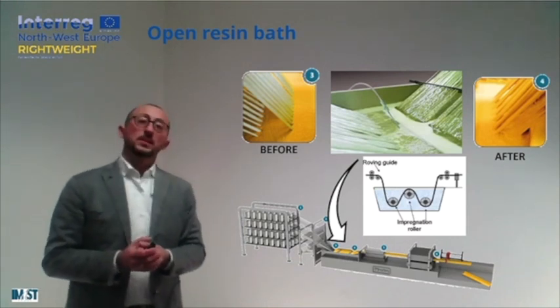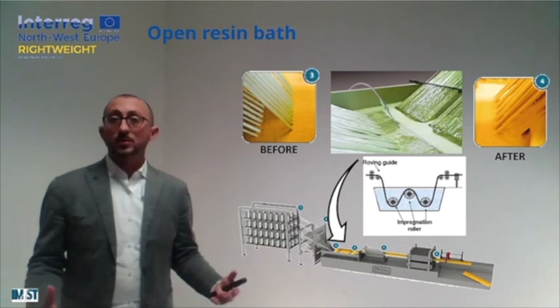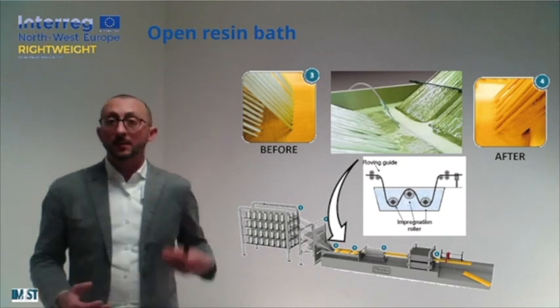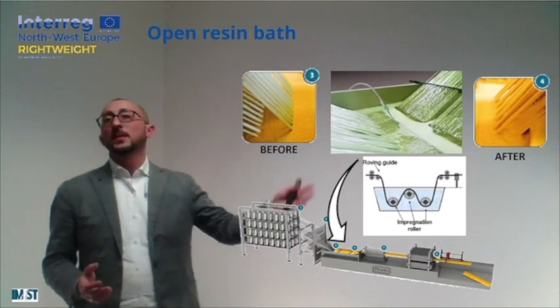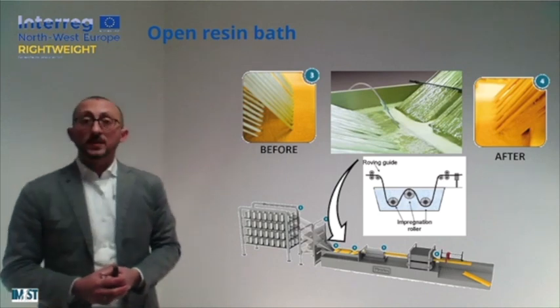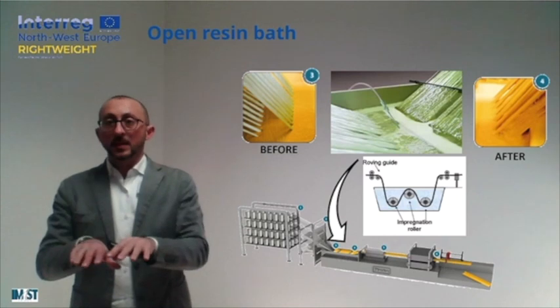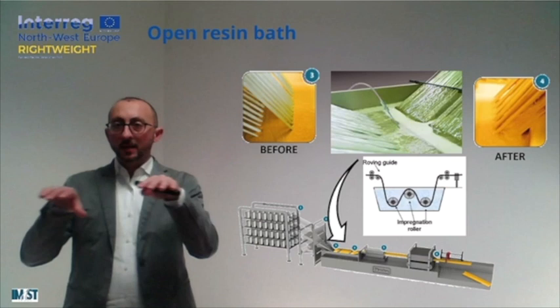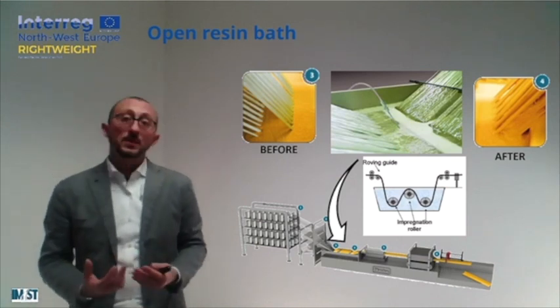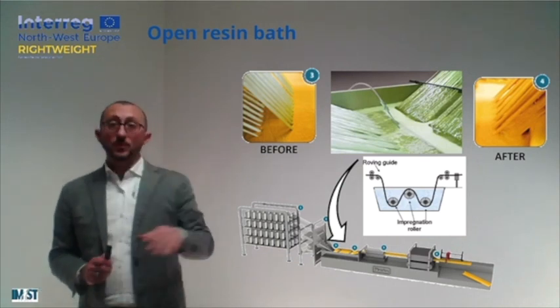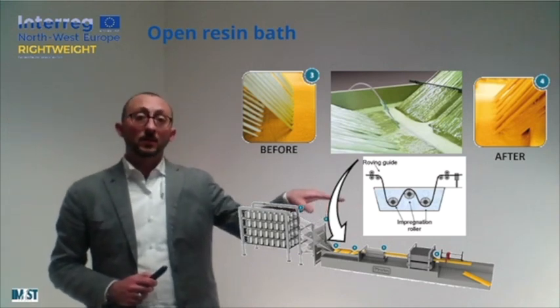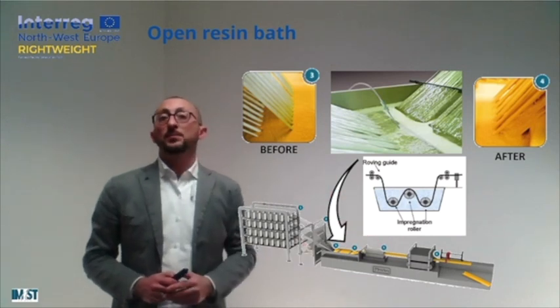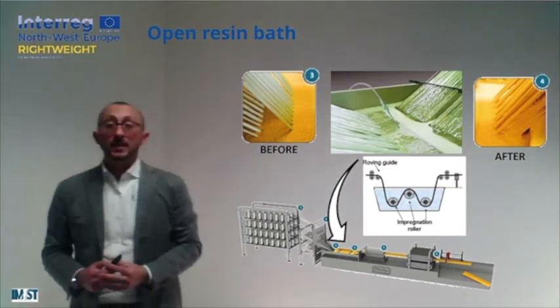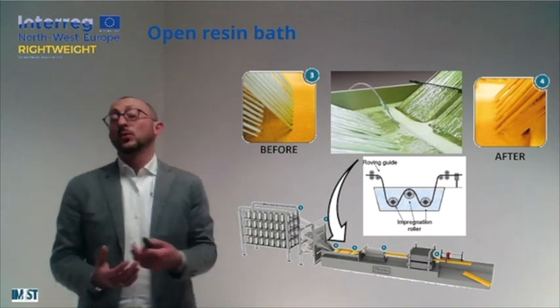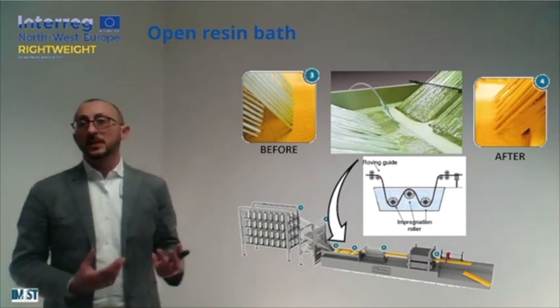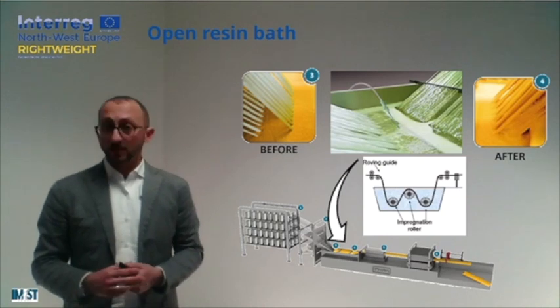So another interesting point about the open bath is that for large production using pultrusion, the resin inside the open bath can be added continuously as soon as it is taken away with the fibers. And in order to avoid a layering effect, meaning that the old resin will stay on the bottom of our tank and then we go layer by layer, putting in new resin, but different layers will have different histories, typically the fibers are forced to follow a path similar to the one that you can see here. So reaching the bottom of our open bath and then moving up and down again and then outside. This will create some kind of mixing of the resin and also will provide some kind of first in, first out strategy for the movement of the resin itself.